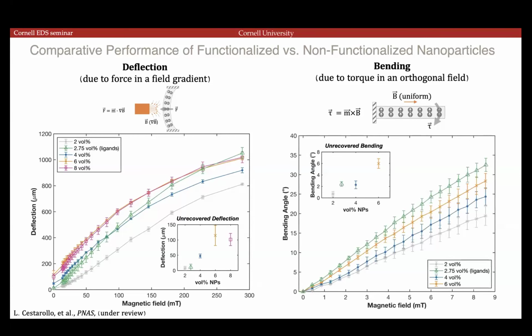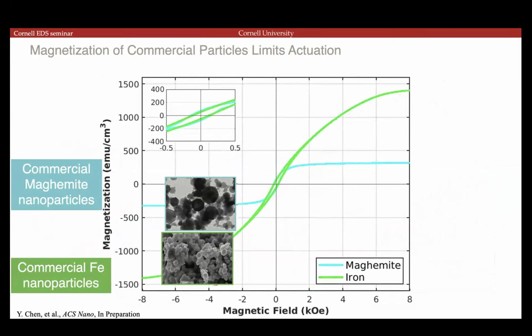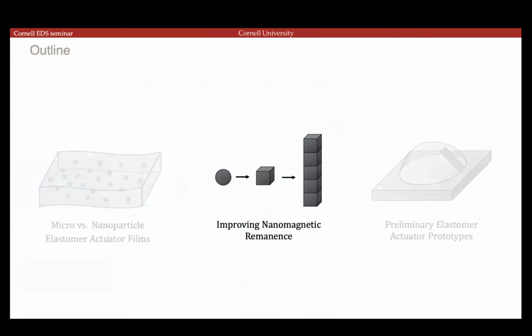But this is all still with commercial nanoparticles, and I said that a lot of our work in our group is making our own materials. So these are the curves of the typical magnetic iron oxide particles that are used in the literature, and you can see what the magnetic moment is for that. And iron, both of these have a very low remnant magnetization. So one thing that we try to do is improve the nanoparticle composition itself and increase its remnant magnetization. And that's where I'll get to the second portion of my talk.